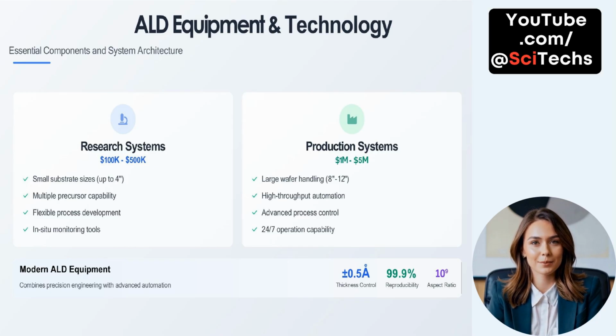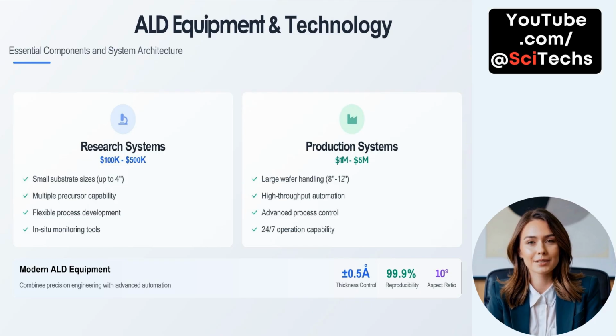On the other hand, production systems are engineered for large wafer handling, supporting sizes between 8 to 12 inches. These tools are priced between $1 million and $5 million and are built for high-throughput automation. They feature advanced process control systems and are capable of continuous 24/7 operation. Modern ALD equipment combines precise engineering with smart automation, achieving sub-angstrom thickness control of plus or minus 0.5 angstroms, reproducibility as high as 99.9%, and compatibility with extreme aspect ratios up to 10 to the power of 9.